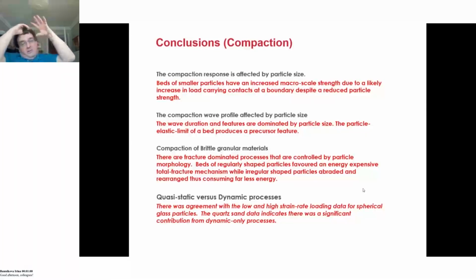The compaction is fracture dominated and heavily dependent on particle morphology and flaw density. So beds of nice regularly shaped particles, you need a lot of energy to get fracture to occur, and it all tends to occur at the same time. Whereas if you've got irregular beds, you can get some localized fracture occurring in individual grains, and so you've got a more gradual change in the process.